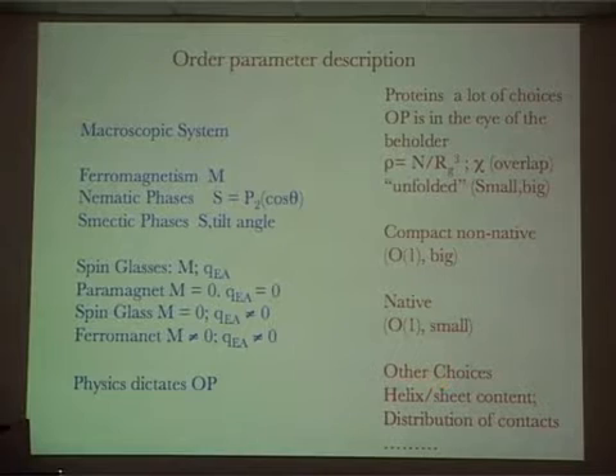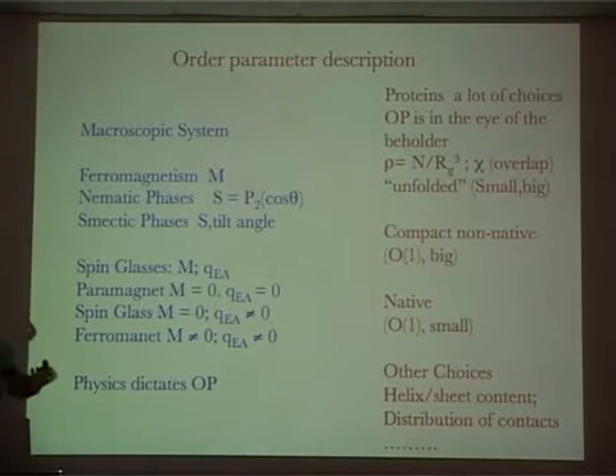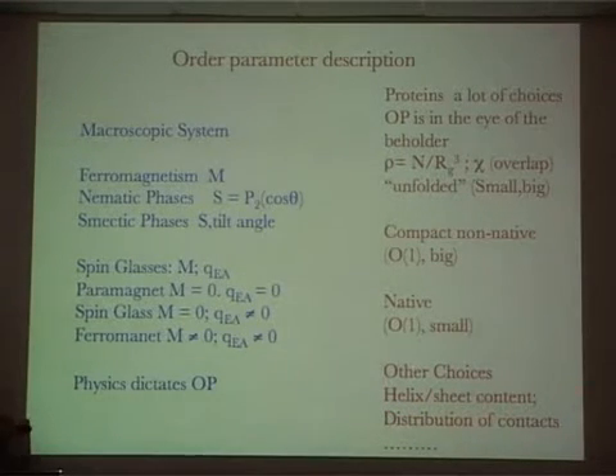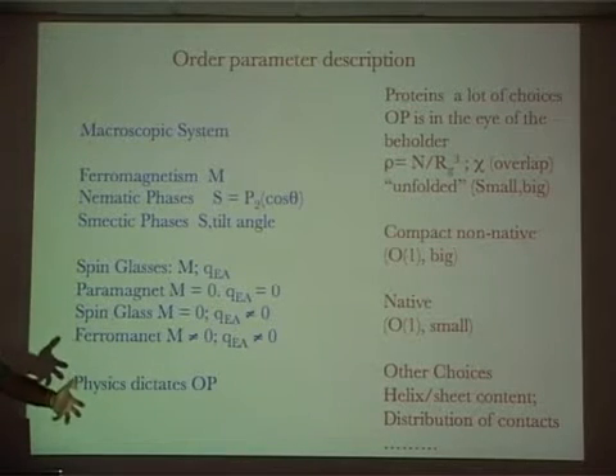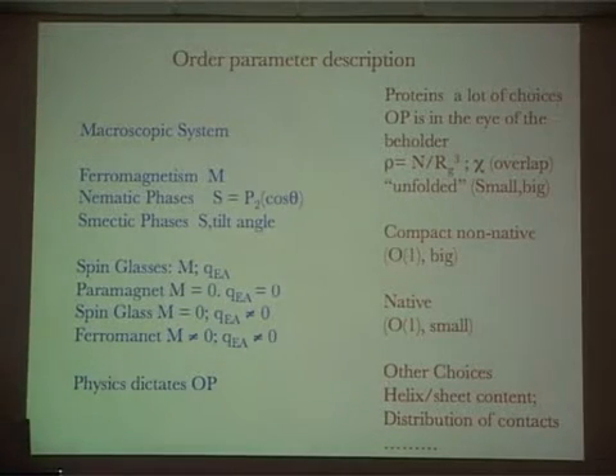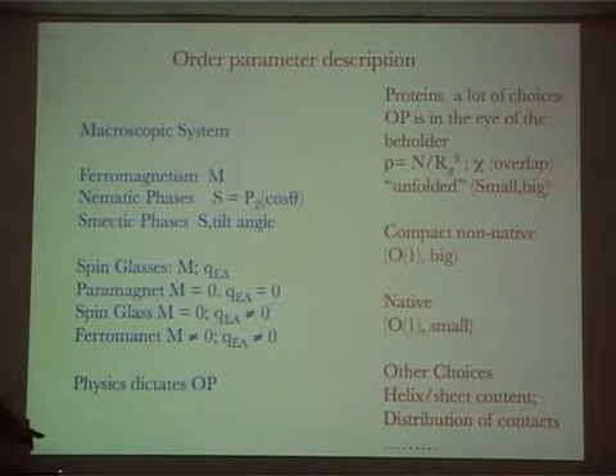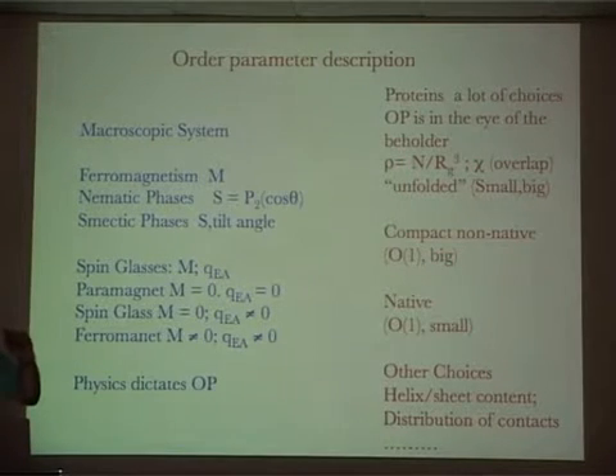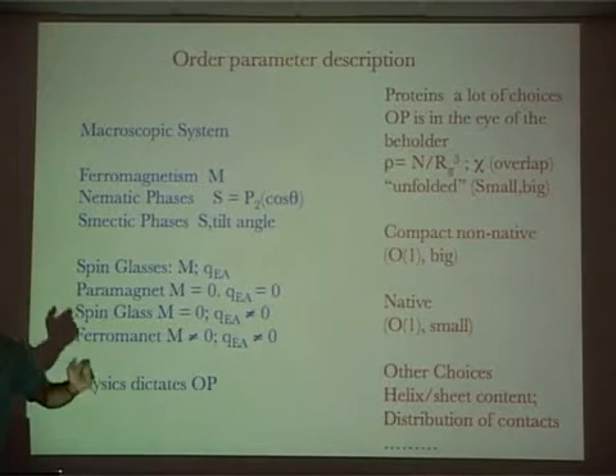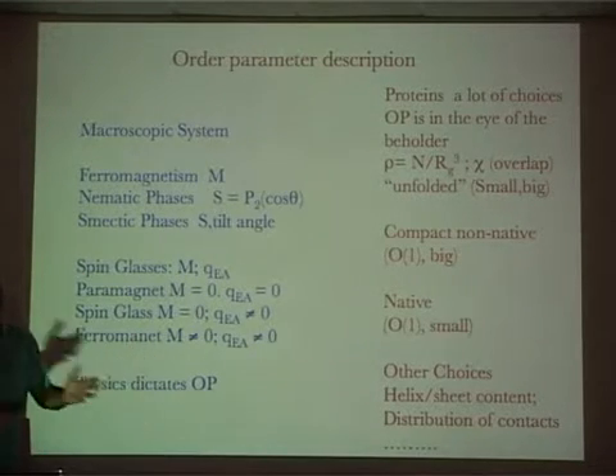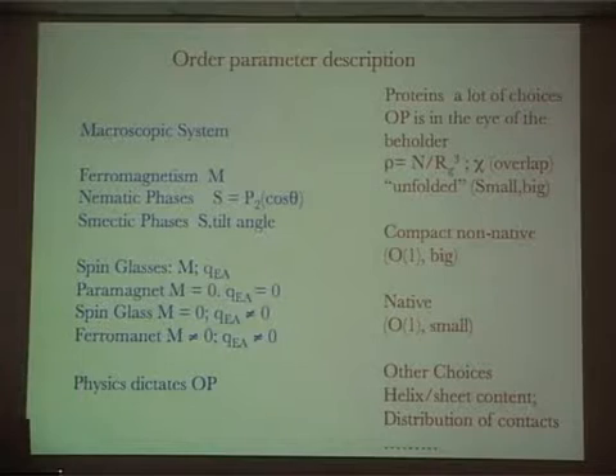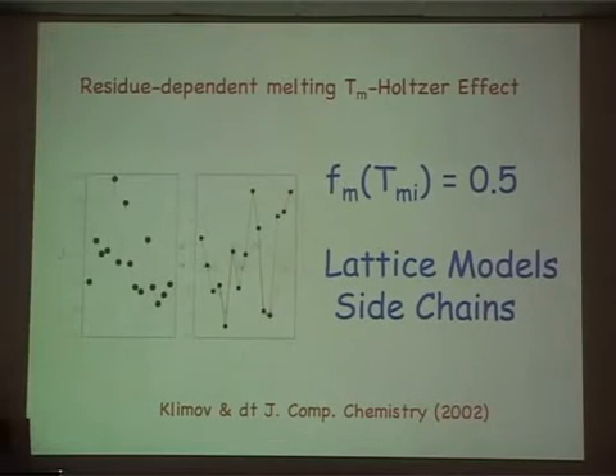I could insist, by looking at the native structure, that my order parameter should be helix or sheet content, distribution of contacts between various residues, distribution of helices, anything that you can think of should be the description of the folded state, and therefore unless you measure my order parameter, I won't agree that the molecule is folded. This may seem like a silly intellectual talk, but in fact it has got real consequences, because you can use different experimental measurements for these different order parameters, and they might tell you slightly different things about the way ordering actually takes place, and that's what I'll show you both experimentally and otherwise.